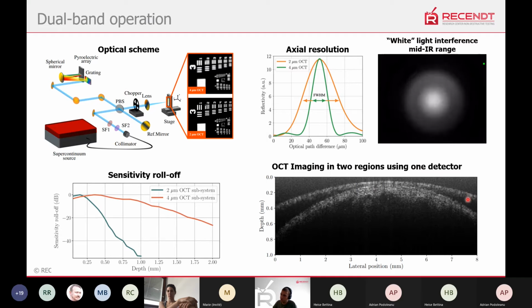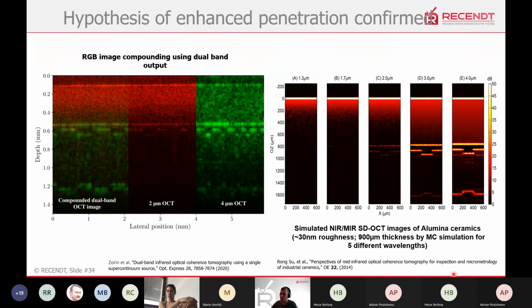Yeah, and if we have no spectral filters, it would look like that. So this would be the OCT image at 4, and this would be at 2. And these two regions give us different insights into materials. And since they are more or less not completely correlative, but with the same system, it was possible to get images like that when we switch between them or make a scan and combine them in post-processing, so that we get both high axial resolution with our near-infrared part and high penetration depth with the mid-infrared part.